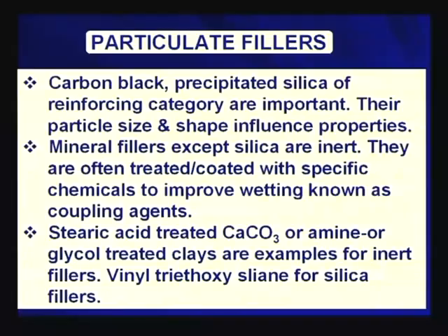Vinyl triethoxysilane. So this vinyl triethoxysilane contains a vinyl side, meaning organic side, and an ethoxysilane, SiO, on the other side. So it will make a coupling between silica filler and the polymer. So here also stearic acid, being organic in nature, has one carboxyl group, a polar side that will be oriented towards the calcium carbonate side, and the organic chain will remain on the other side that will mix with the polymer. So this is the basic principle. Okay.